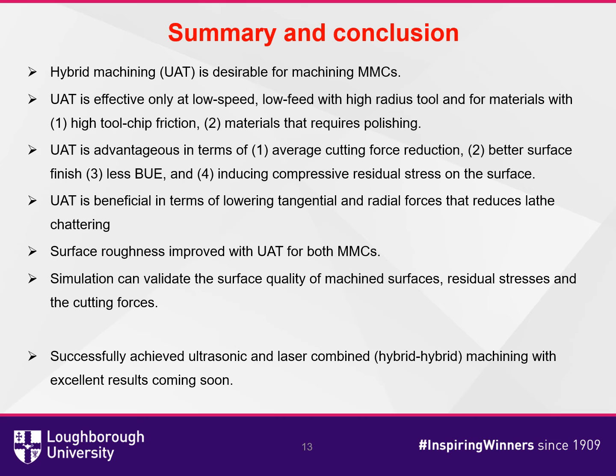To sum up, hybrid machining UAT is desirable for machining MMCs. UAT is effective only at low speed, low feed with high radius tool, and for materials with high tool-chip friction, materials that require polishing. UAT is advantageous in terms of average cutting force reduction, better surface finish, less BUE, and inducing compressive residual stress on the surface.